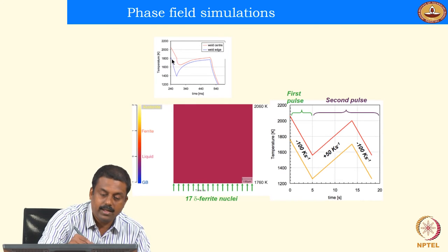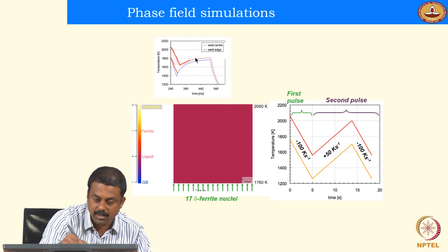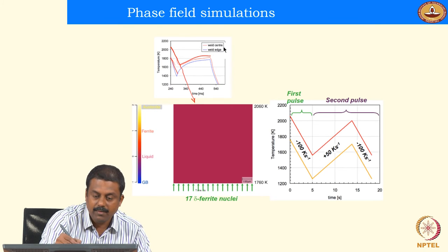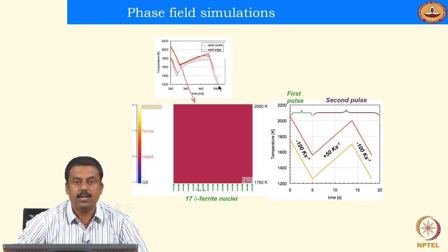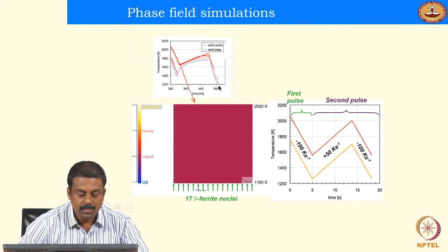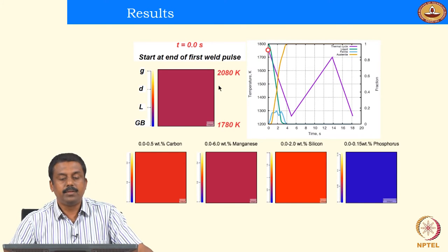So we have simulated the similar weld thermal cycles, where in both the cases, weld center and weld edge, we cool to some temperature and subsequently we take it to another temperature. So in a single pulsing case, we'll continuously cool to room temperature, whereas in the double pulsing case, instead of cooling to room temperature, we'll take it again to some temperature and then subsequently cool it back to room temperature.